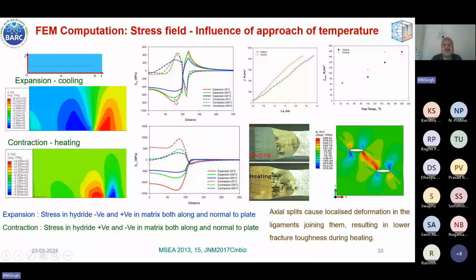And we thought, I don't know whether this is just FEM calculation, we have got some numbers, or whether it will have any effect on fracture toughness. So here we show the plot of J parameter with the delta A. For heating curve, you can see J curve is like this. For cooling curve, it is like this. And in fact, the plot of this J max with test temperature is shown over here.